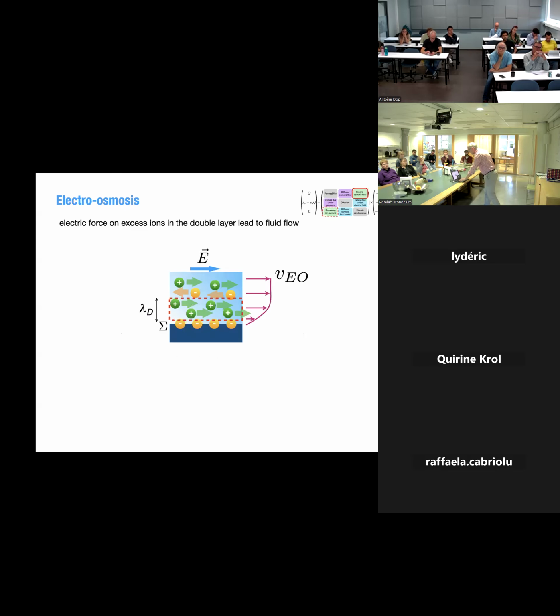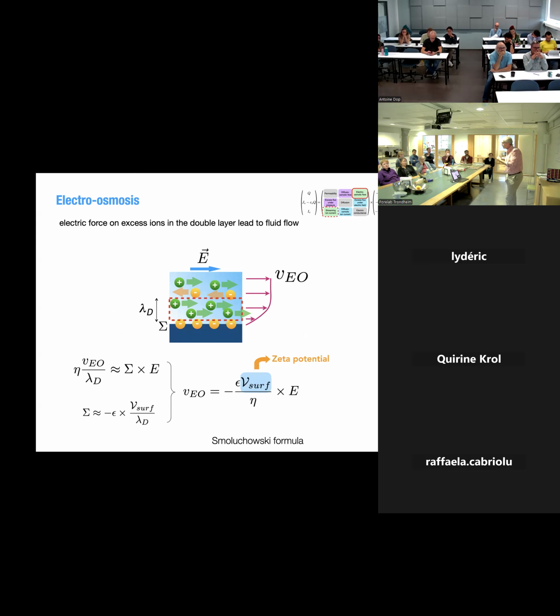In this matrix, one aspect is electro-osmosis. For example, electro-osmosis is the flux of water under an electric field. You can do the Smoluchowski approach, but let me give you a scaling law approach, which will help for the next step. Electro-osmosis is simply the fact that in the bulk, you have no electric force because you have as many positive ions as negative ions, so the force is zero. Close to the surface, in the electric double layer, you have an excess of counter-ions. So there is a force only within the double layer.